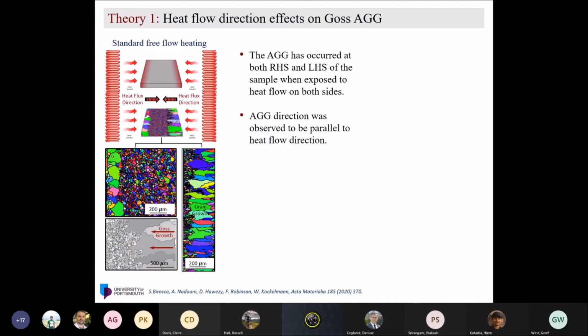And if you click next, we did some experiments on the effect of the heat flow direction on abnormal grain growth. That was the first experiment we did. We put the primary annealed sample in a furnace, and we directed the heat flux to be exactly on both sides, not the top and bottom, but rather the left-hand side and right-hand side. And when we did the EBSD analysis after this, we found that abnormal grain growth occurred on both sides, right-hand side and left-hand side, when exposed to the heat flow from both sides.